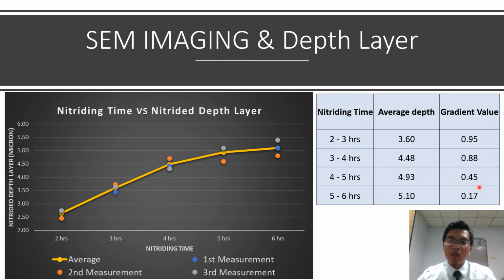the previous one, which shows that the reaction rate or the nitride depth layer formation is half as fast compared to the previous one. And from 5 to 6 hours, the gradient value is 0.17, which is almost one third of the previous value, 0.45. This shows that after 5 hours of nitriding time, the depth layer formation becomes the slowest compared to all the parameters set in this project.